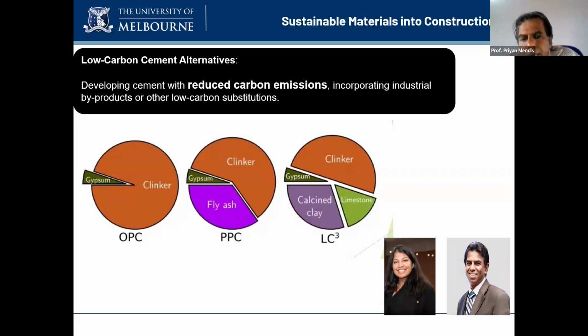So with the calcined clay, rather than fly ashes, we take the clay from the waste material and heat it up to about 700, 800 degrees, and that gets a calcined clay. And then with limestone, LC3 is really replacing a lot of the cement clinker. That way we can reduce the emissions by half or more.